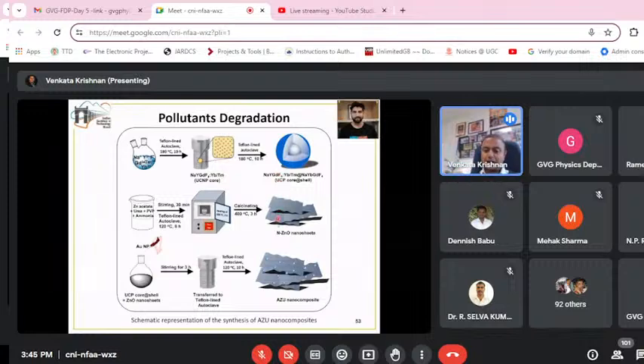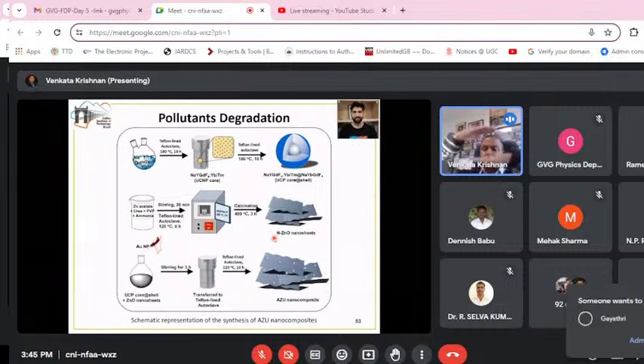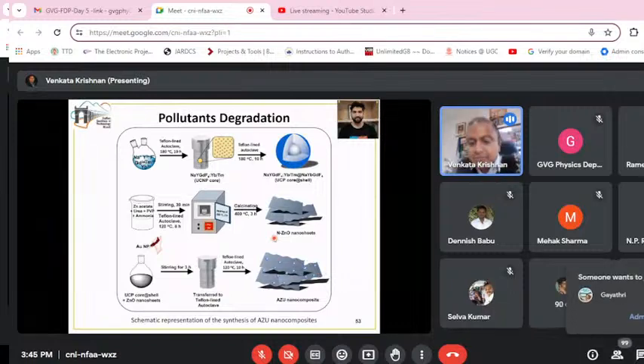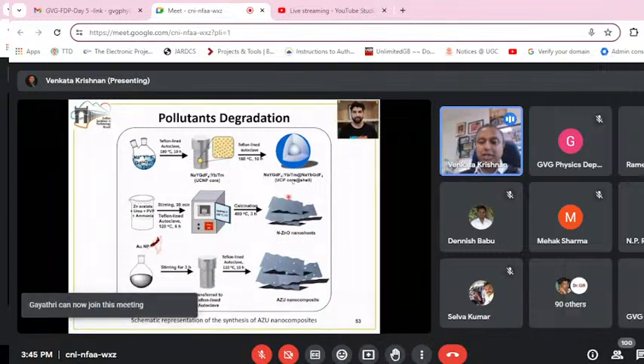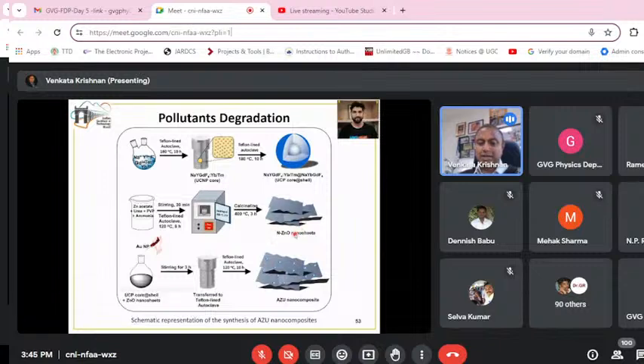Then we prepared another material, n-doped ZnO. As we know, ZnO is a semiconducting material and a UV light active semiconductor. When we dope it with nitrogen, we are tuning the band gap of the semiconductor, in this case to a level such that the emitted UV radiation gets absorbed by this n-doped zinc oxide.